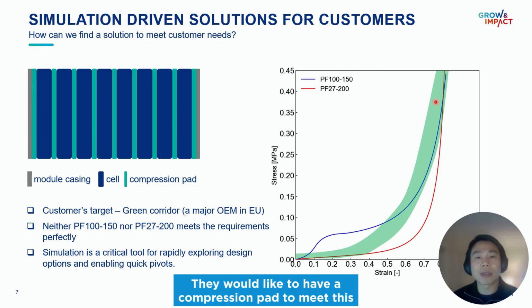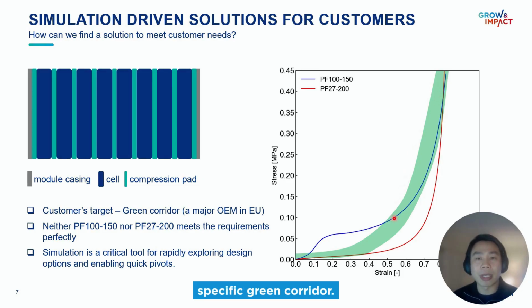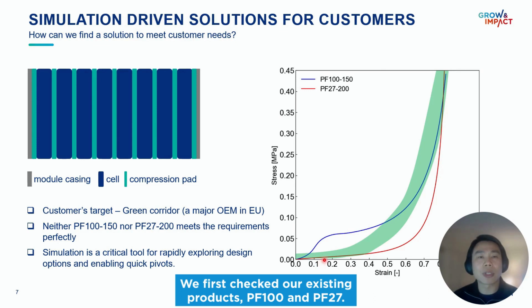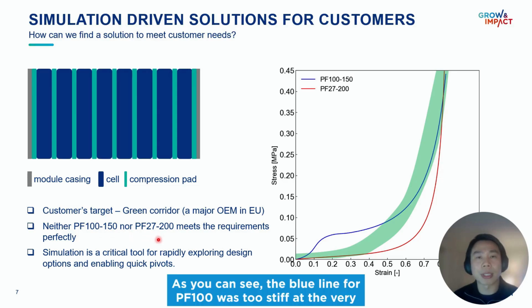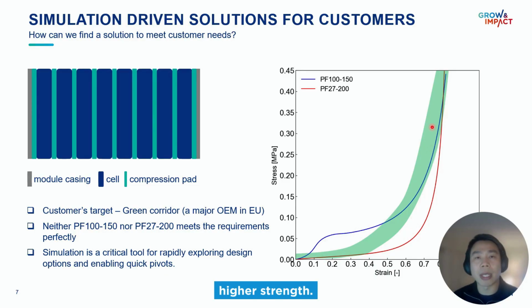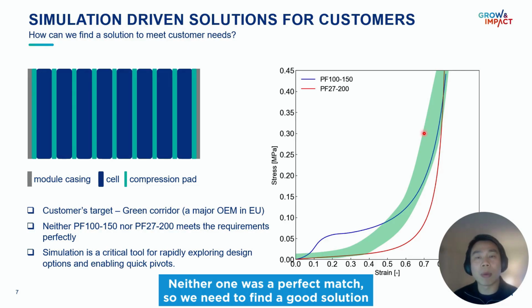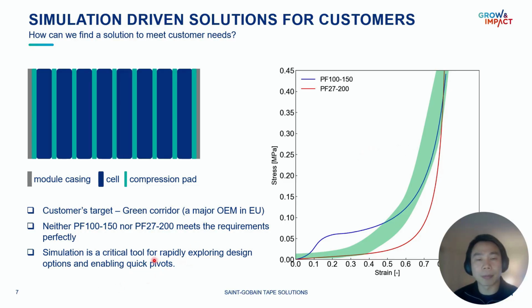And they would like to have a compression pad to meet this specific green corridor. We first checked our existing products, PF100 and PF27. As you can see, the blue line for PF100 was too stiff at the very beginning, and the red line PF27 was closer but fell out of the corridor at a higher strength. Neither one was a perfect match, so we need to find a good solution in this case.